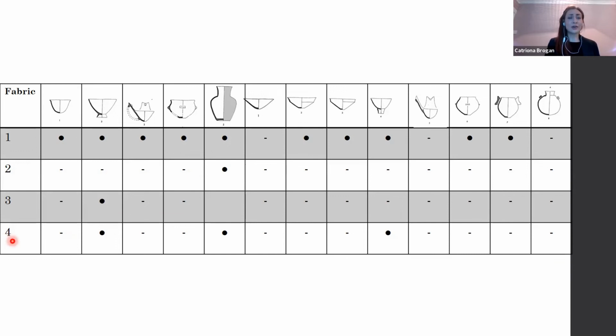And then fabric 4, which is the coarseware, is used to produce this neck jar, and also, quite surprisingly, the pedestal bowls, because these generally tend to be quite fine-walled vessels, so it's quite surprising to see the coarser fabric used for that.